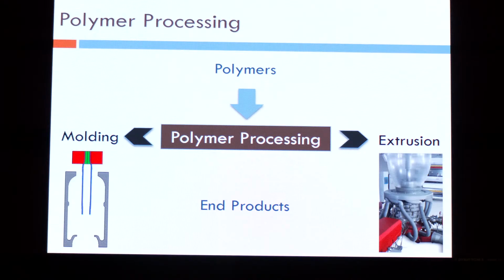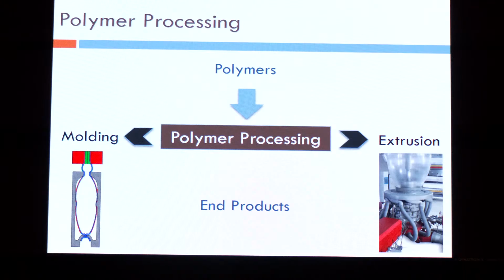And you are basically extruding this liquid melt into a die, and you are pumping air to swell this liquid almost like a balloon. It actually swells like a balloon. And again, you will see in this process two things important. First, you have to flow the liquid. So it has to behave like a liquid. It has to flow out of a die into a mold. And when it enters the mold, you have to blow air in it, and it swells almost like a rubber, right? Like you can blow a rubber balloon. This liquid will actually blow into a bottle. So in industrial scale processing, you see that it has to behave like a liquid in one case and an elastic liquid in the other case.